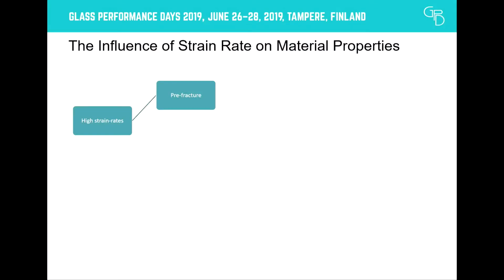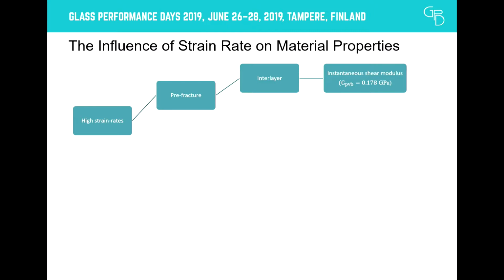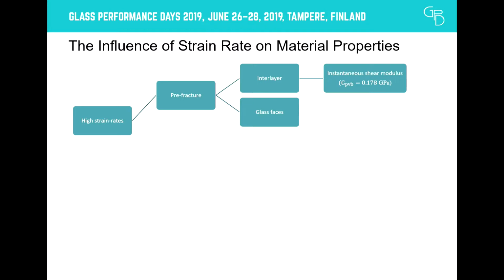The high strain rates affect the response of laminated glass panels both in the pre-fracture and the post-fracture response. In the pre-fracture response, the interlayer can be assumed as an elastic plastic material with strain hardening. This allows significant simplifications when developing analytical models, especially when compared with low strain rate analysis that requires full viscoelastic analysis. The elastic plastic with strain hardening response has been observed in many publications that have performed tensile tests at high strain rates. The glass layers are also affected by the high strain rates, as cracks require time to grow.